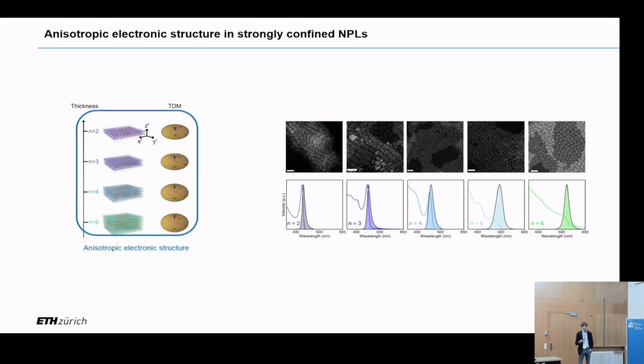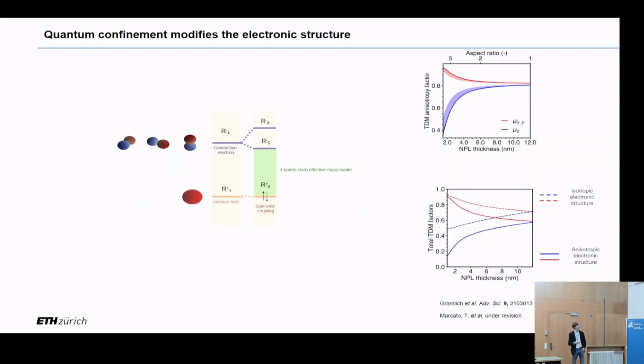Next, the last case study of my presentation is, well, what happens if we have strongly confined nanocrystals, where the electronic structure gets significantly modified, the emission gets significantly modified. Well, you cannot ignore the details of the electronic structure anymore. And it turns out what we could use is we implemented a 4-band effective mass model, which was recently developed specifically for lead halide perovskite nanoplatelets. And what this model helps us understand is the effect of the mixing between these 3 states, which form the conduction band of the nanocrystals.